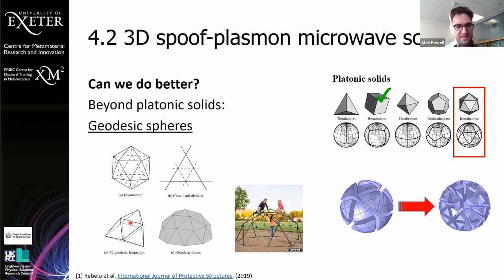And we just do this by taking equilateral triangles in each existing triangle of the icosahedron and stretching the vertices so they meet the surface of a sphere surrounding it. And that allows us to have almost identical triangles at each of the... how many faces is it? 20 times 4, so 80 faces we have now. So we have much more detailed structures here.